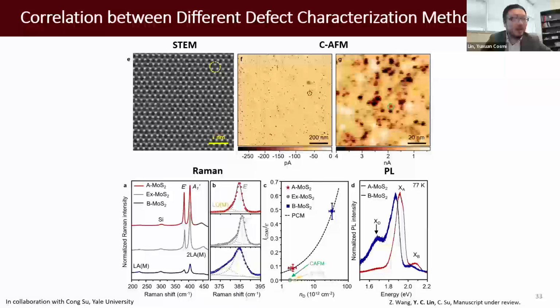This is a relatively good quality sample. And we compare the defect density extracted by these three methods shown in this plot, especially here. If you look at the x-axis, they match with each other very well. For the last one, there's another point for the STEM results. The defect density is slightly higher than the Raman and conductive AFM results. That may be because of some kind of defect generation due to the E-beam irradiation.